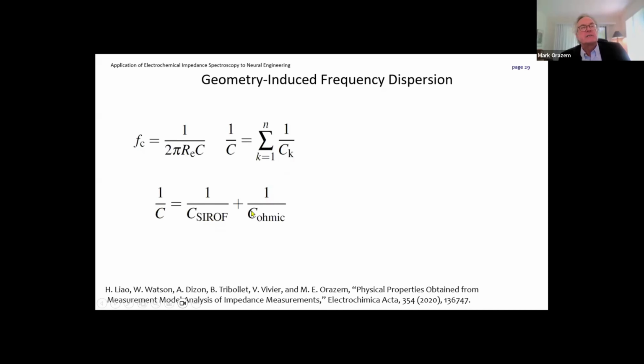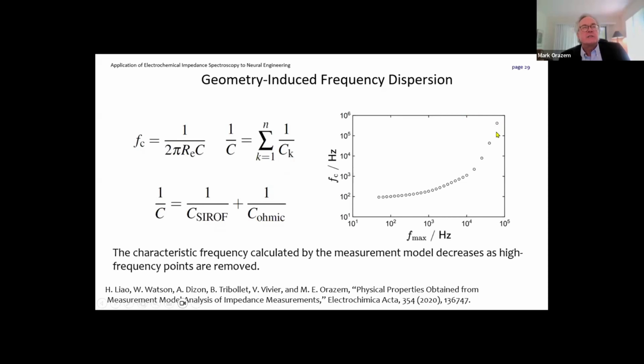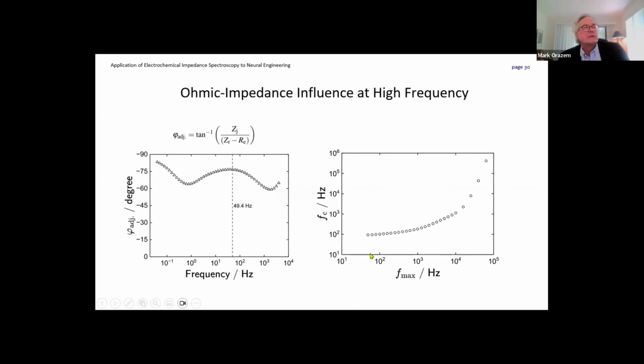Now, this capacitance, 1 over C, is actually the sum of the inverse of the capacitance we want and the inverse of the capacitance that we don't want, which is the capacitance associated with the geometry of the electrode. So our approach to this problem is to delete high-frequency points. And as we delete high-frequency points, this capacitance contributes less and less, and the overall capacitance becomes larger, causing this characteristic frequency to become smaller. And so we did this.